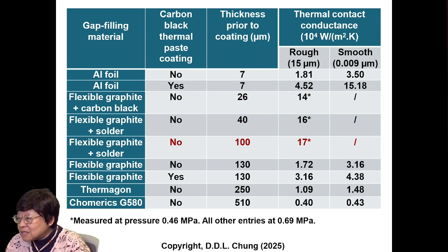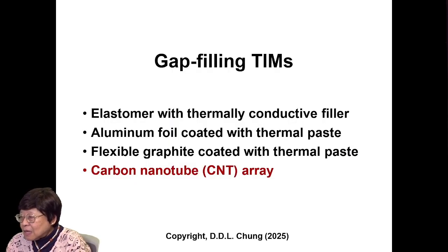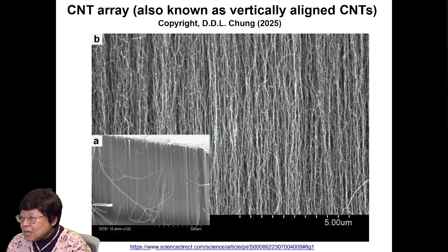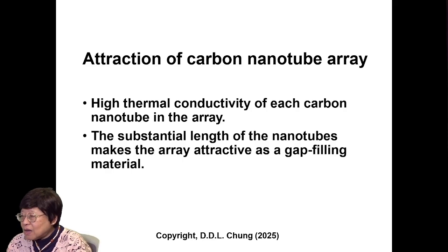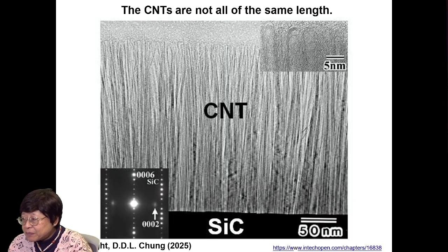And the very best is the 17, which is a flexible graphite with the solder particles incorporated. How about carbon nanotube array as gap-filling TIM? The CNT array is also known as vertically aligned CNTs. And you can see it's vertically aligned. The attractions are high thermal conductivity of each carbon nanotube in the array, and the substantial length of the nanotubes, making the array attractive as a gap-filling material.